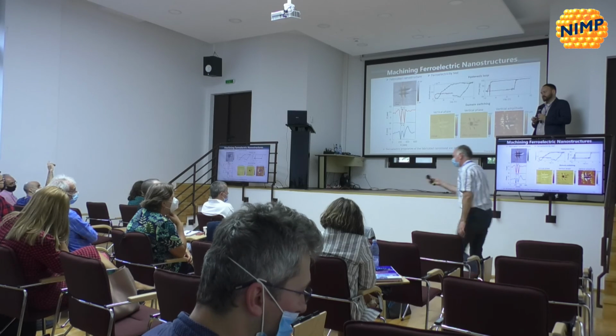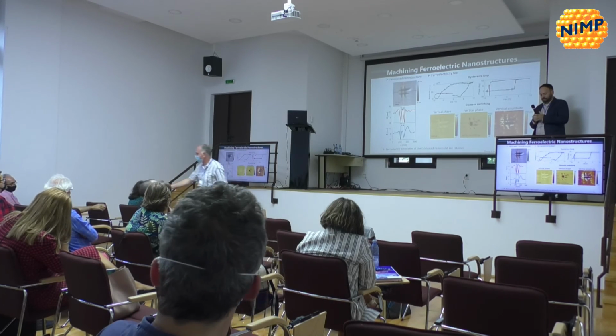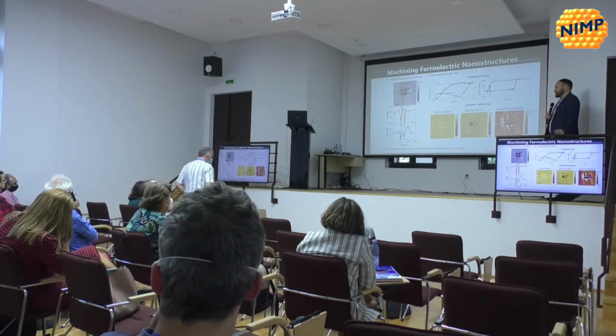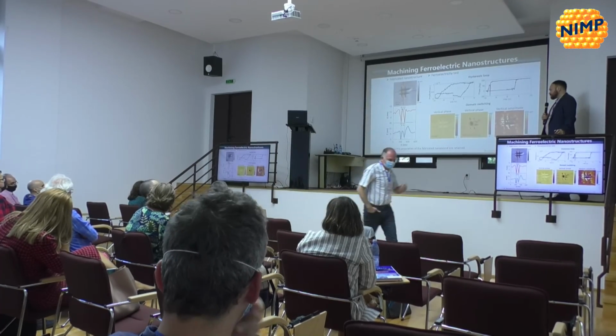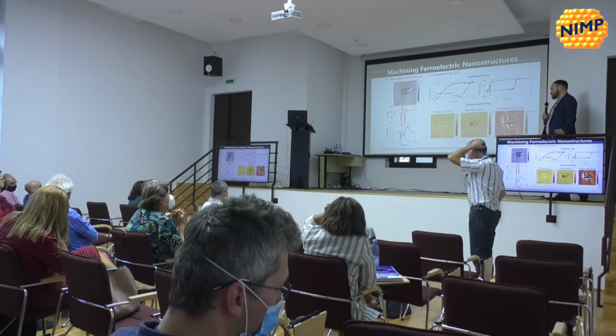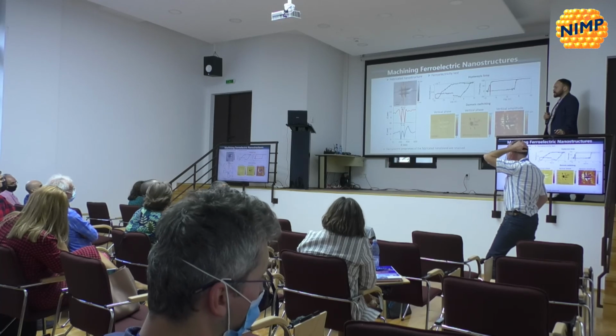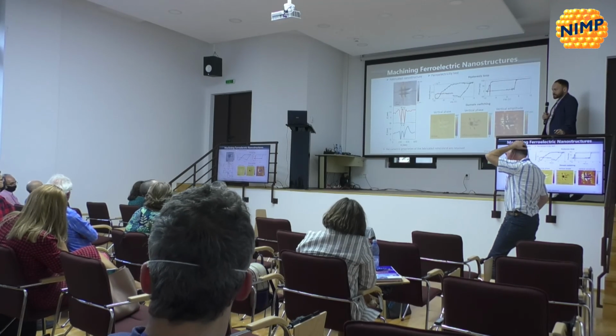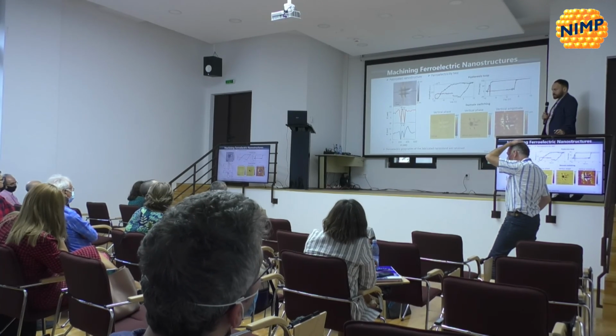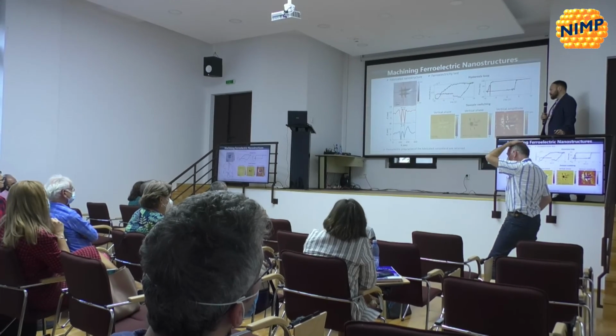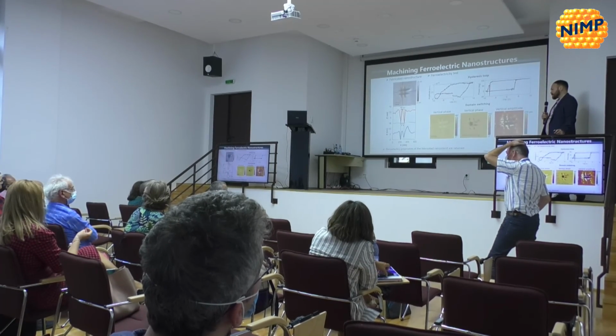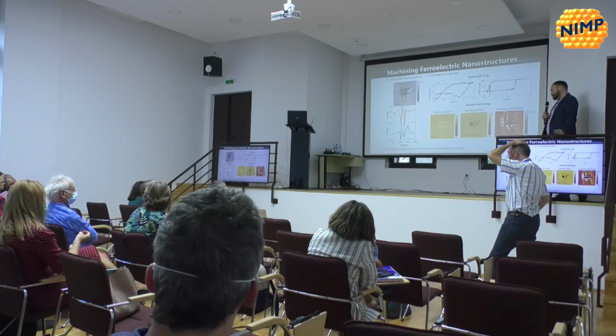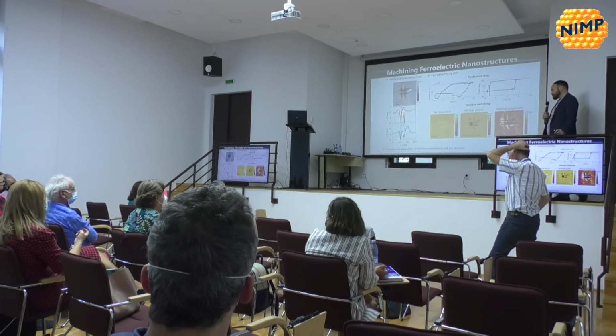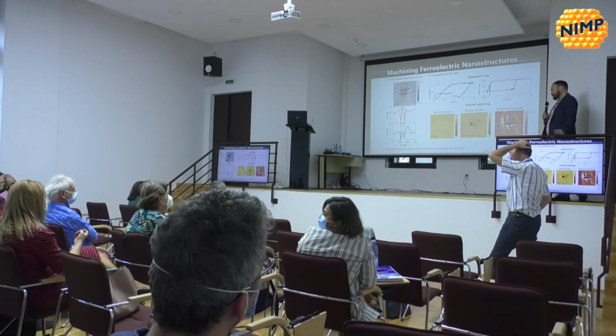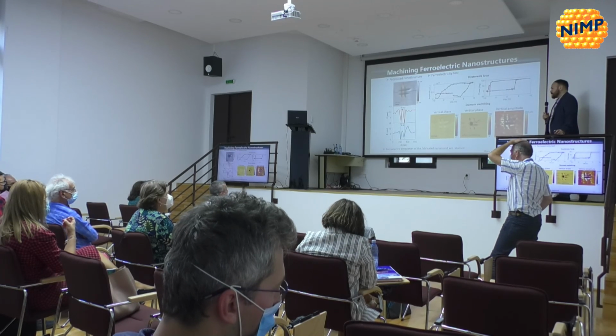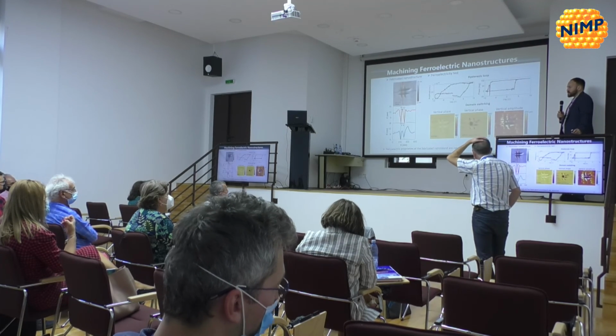Yeah. Okay, anyone? If I understood correctly, you are dumping tens of micronewtons on a basically 25 nanometer square area. So the pressure is huge. Yeah. So have you considered the possibility that the increasing conductivity is due to the fact that you're pushing bismuth ferrite towards a more conductive state, towards a bulk more conductive state? So it's nothing to do with a dead layer. Bismuth ferrite is reported to have a metallic state at high temperatures, so presumably also at high pressures. Yeah, no, that's a good point.